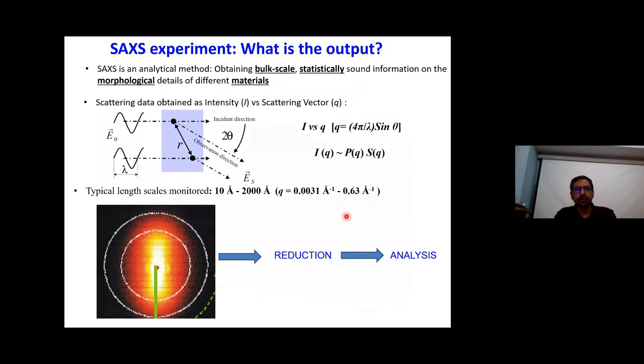In a typical SAXS experiment, you take the sample and pass the radiation onto it, and then you have a scattered radiation on the detector. This is a general equation of scattering. What you obtain is the scattered radiation intensity, which is proportional to P of Q and S of Q. P of Q is known as the form factor of the system. It's actually the scattered radiation from a dilute system. But when you start concentrating that system, the S of Q, which is known as the structure factor of the system, comes into play, which talks about the interactions between the materials. So P of Q will tell you the information about a single entity when it is dilute in the system, but S of Q comes into the picture when you start concentrating the system.